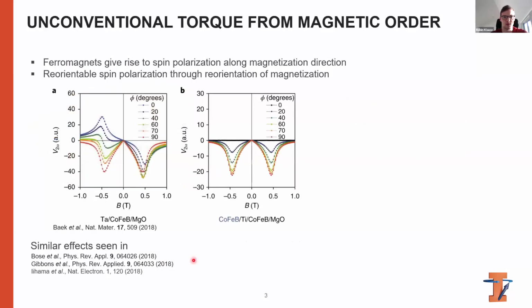One way this has been looked at is through ferromagnetic ordering. Ferromagnets give rise to spin polarization that is along the magnetization direction, and thereby you can reorient the spin polarization by reorienting the magnetization direction.